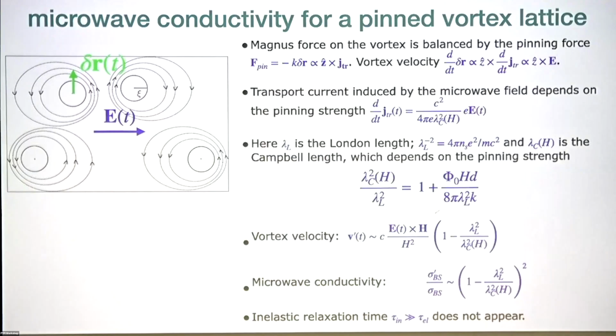And instead, what I will discuss is, in my view, a more interesting case of microwave conductivity at strong pinning. There, the mechanism of appearance of the Debye contribution is, I think, much more interesting. So let me just discuss the setup. Now I would consider a vortex lattice, which is strongly pinned and deformed, irregular. And now we have these vortices. We apply an AC microwave field. This microwave field induces the Magnus force, which induces AC displacements of the vortices from the pinning positions. And the question is, what is the conductivity?